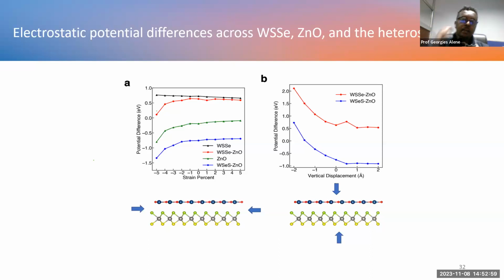I think for the zinc oxide, because of the buckling, as we have investigated, when we apply strain, this buckling is significantly affected by the strain. And the zinc and oxygen have different charge, and this creates some dipole moment. We actually expected the same because S and Se have a charge difference, and there is some intrinsic dipole moment, and it might be affected by strain. But when we investigated the effect, we got this value, and our study shows that it is not significantly affected by strain when you apply strain on WSSe. That's what we have got.